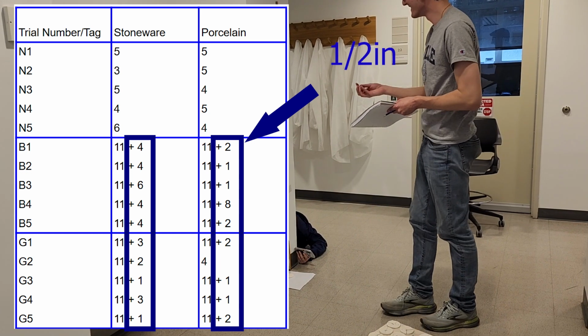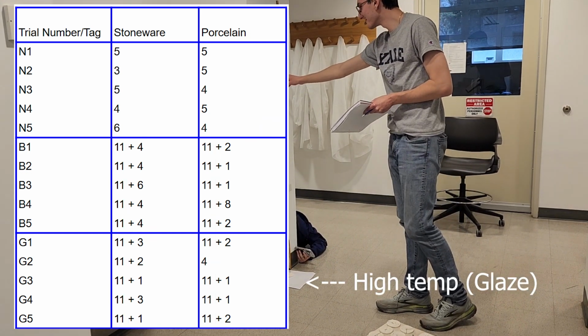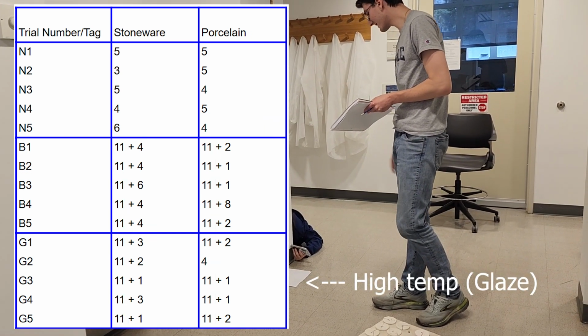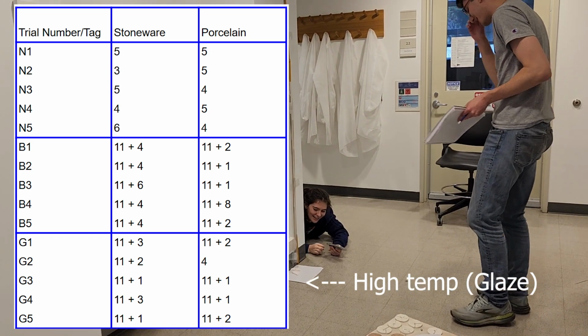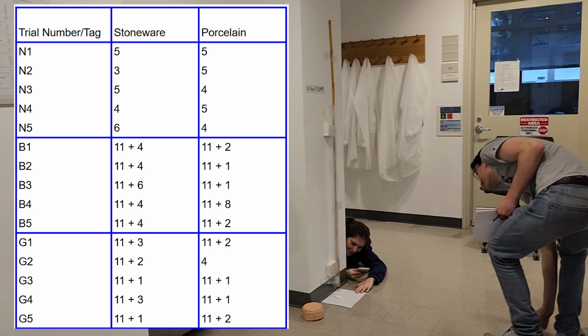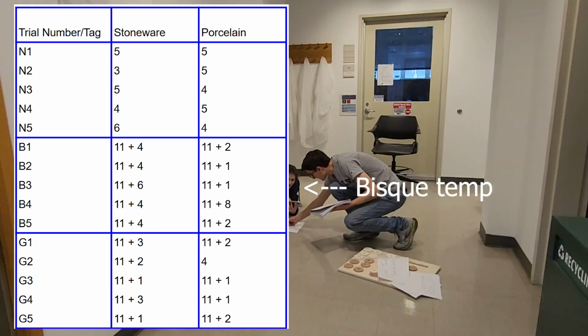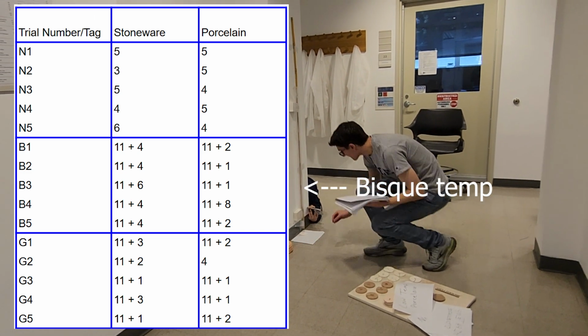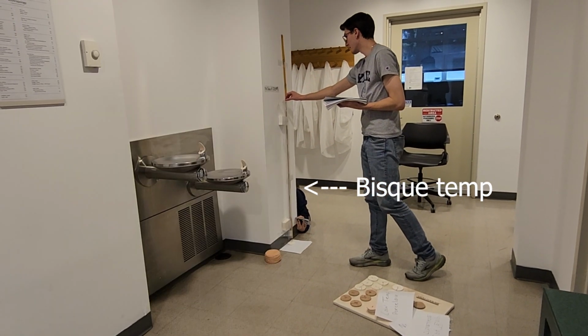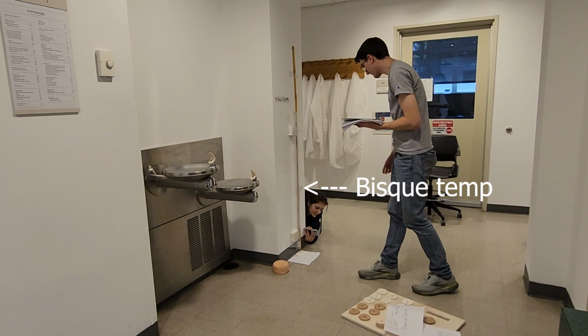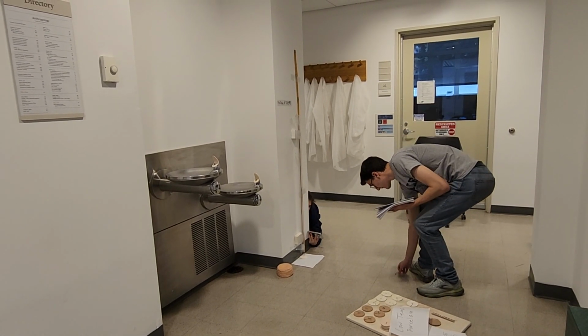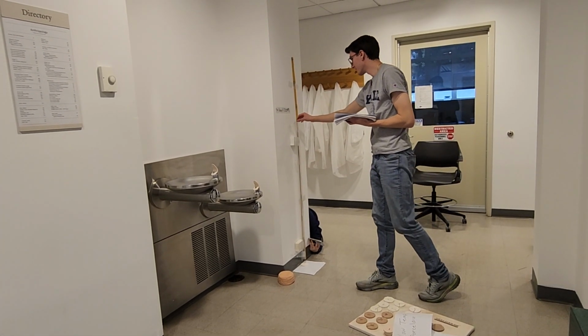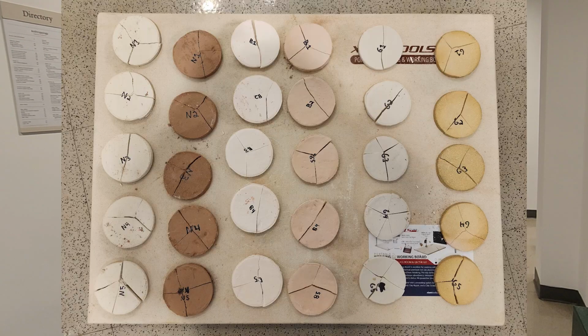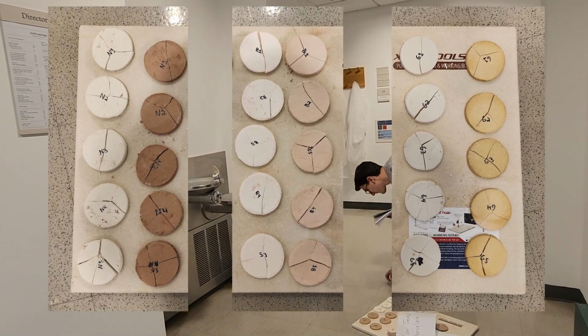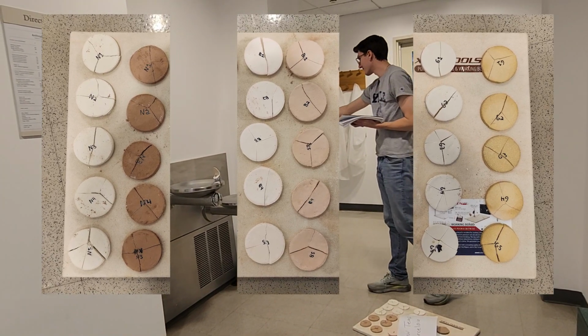The high temp clays broke after taking on an average of 2 drops of the larger ball for the stoneware and 1.5 drops for the porcelain, following the first 11 drops with the smaller ball. The bisque temp clays were overall the most durable, needing 4.4 drops of the larger ball for the stoneware and 2.8 drops for the porcelain to finally break. So, this tells us that firing temperature does play a role in durability, and that medium temperatures, such as the bisque temp, are best for making ceramics most durable.